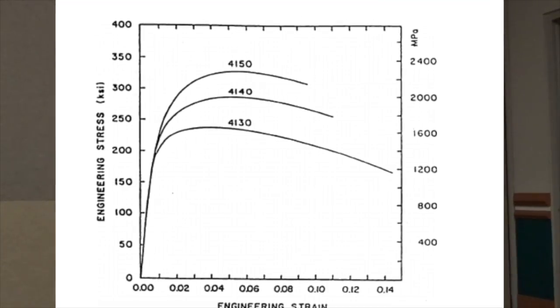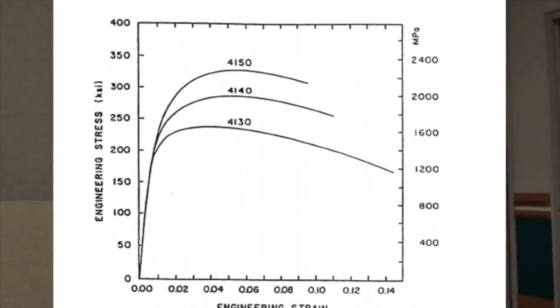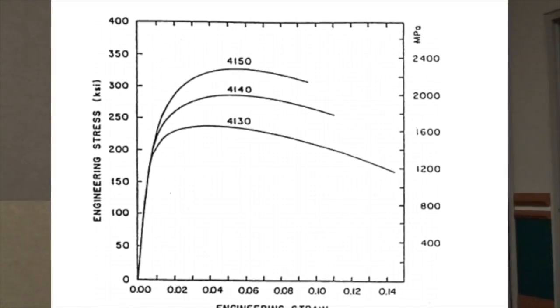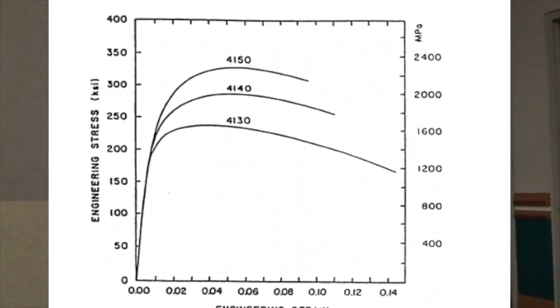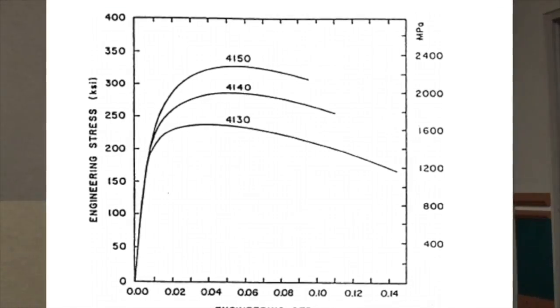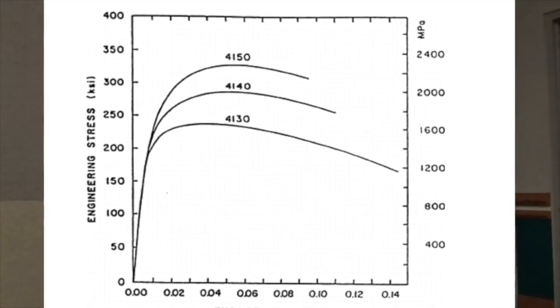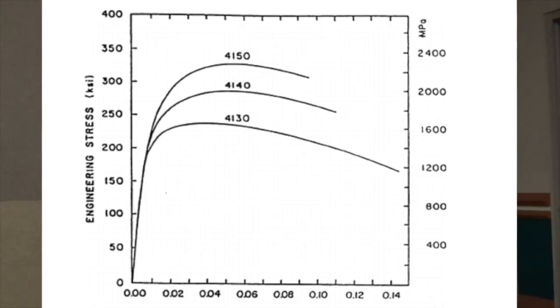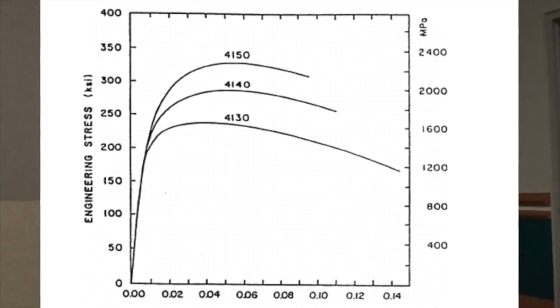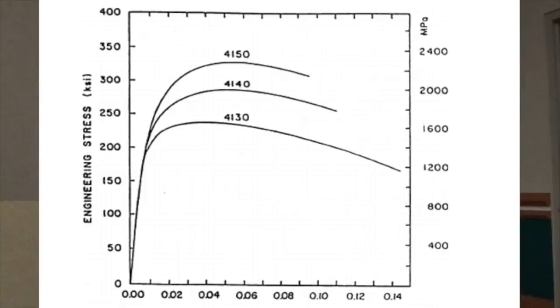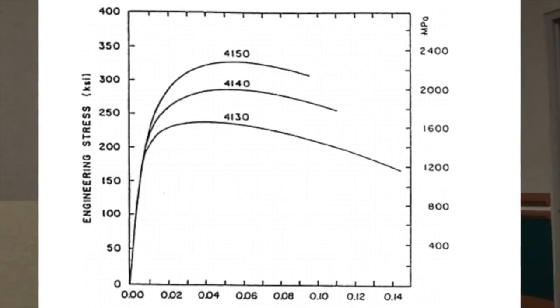in the alloy. And as you increase the carbon, it increases the hardness. But as you see, those lines stop sooner. The 4150 stops sooner than the 4130 does. And you can pretty much see that if you were going to plot the areas again, the 4130 would have the most area underneath. So it would in fact be the toughness king.